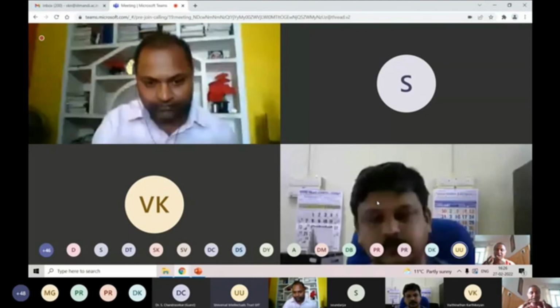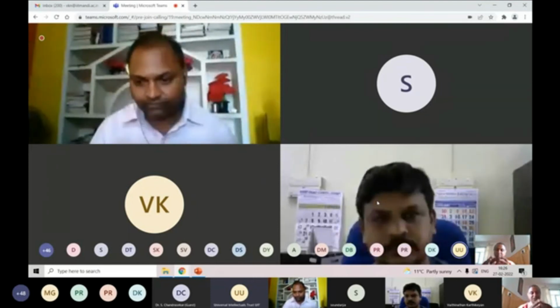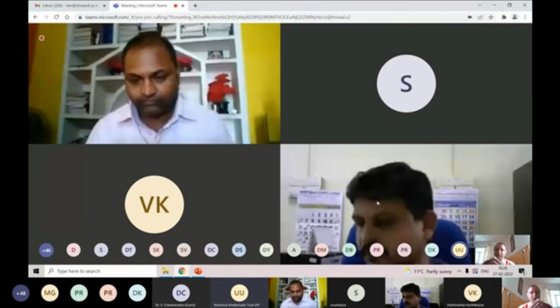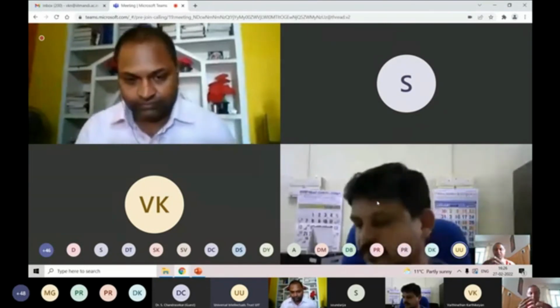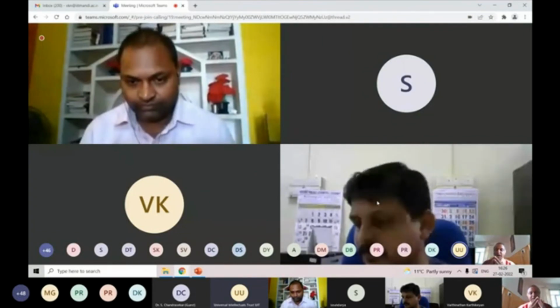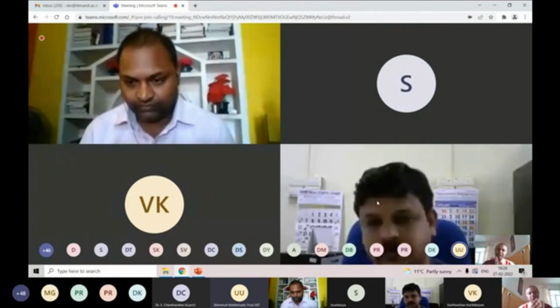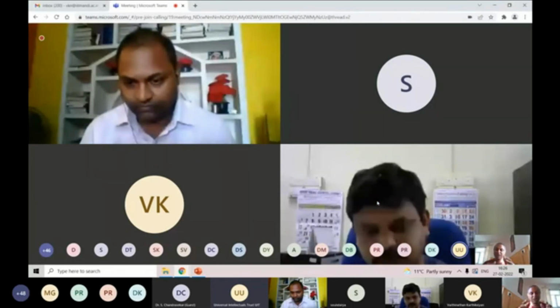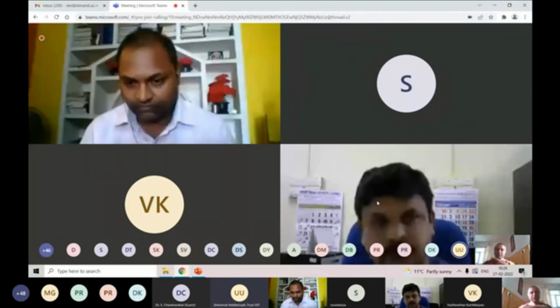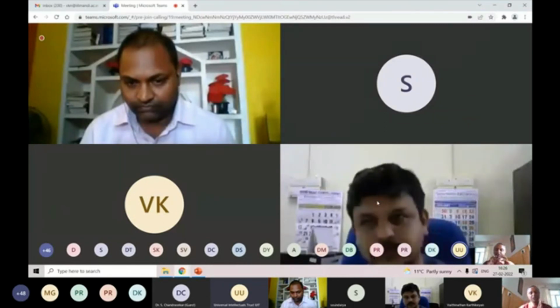So the first work which I discussed, the zinc oxide with the MoS2 and RGO, this could be one of the good catalysts if someone wants to take it up for commercialization. And further, we could fine tune that catalyst much more nicely in some of our subsequent works, which we have fine-tuned with defect rich MoS2 instead of a normal MoS2, and also the zinc oxide, instead of balls, we could have some flat two-dimensional type of structures. So we can even further fine-tune those catalysts if we want to take it to the industry.